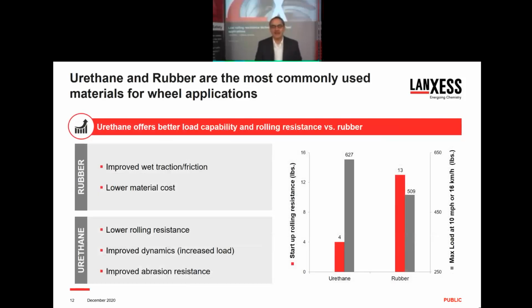In the industry today, most materials for wheels are rubber or urethanes. And in this case, we're going to compare a standard rubber with one of our high-end urethanes with a focus on rolling resistance. So when you're looking at the two categories, the main benefit of rubber that we see a lot of is improved wet traction. If you need very good wet traction, rubber is usually the way to go. If you're looking for the lowest cost initial investment, rubber is the way to go.